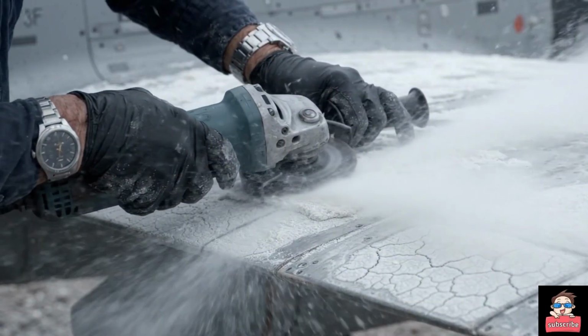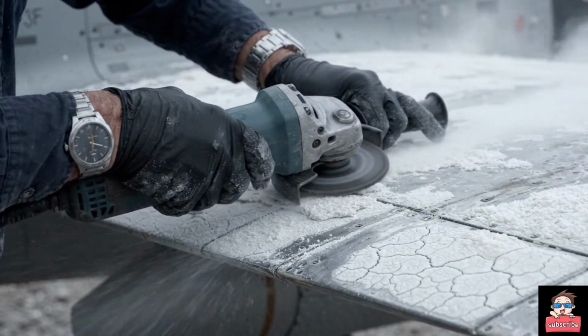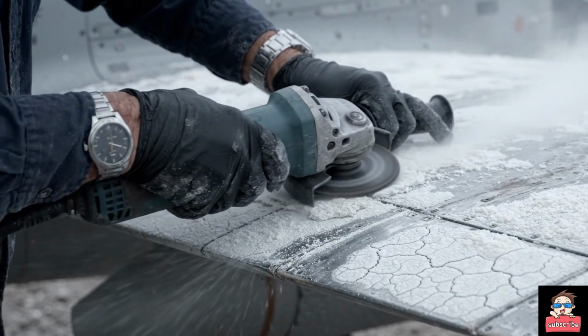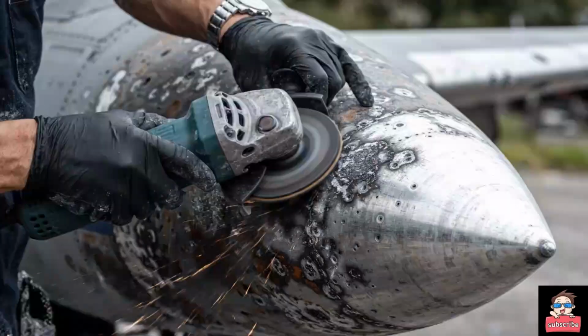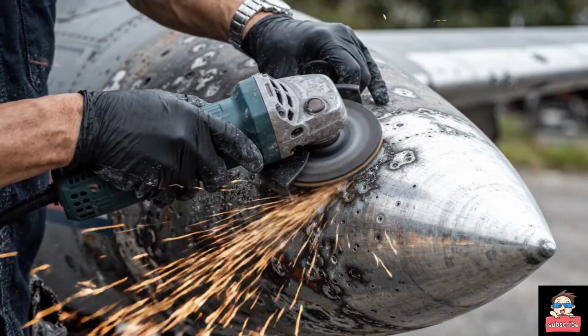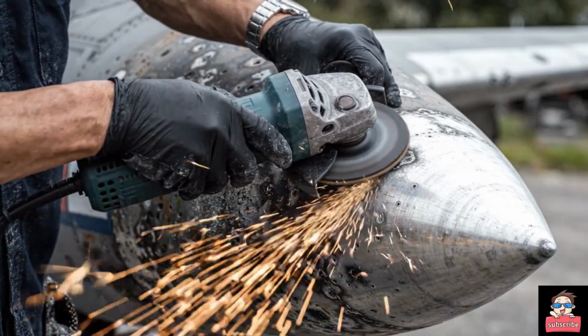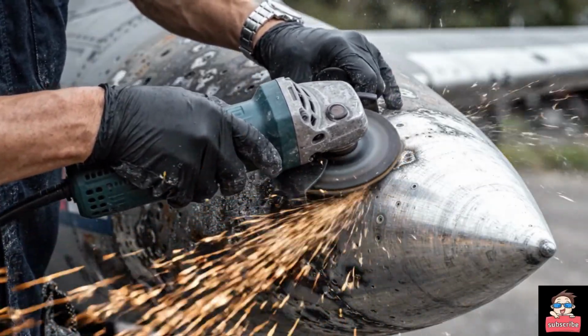Ripping through the calcified mineral block, the wire wheel breaks up the stubborn deposits, clearing the hidden alclad skin below. Grinding away the deep surface oxidation layer, the conditioning disc strips the rot, leaving clean military silver trails behind.